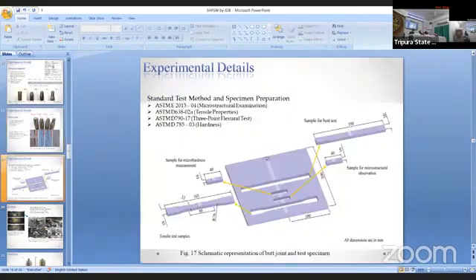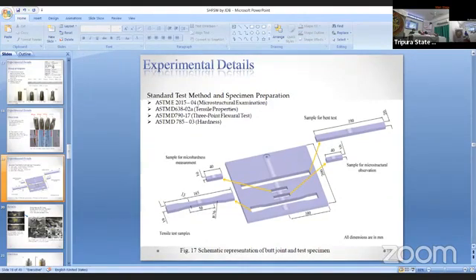For testing the quality of the weldment, we have used different standard test methods and specimen preparations. For example, for microstructural examination, we have gone for ASTM E2015. For the tensile property test, we have gone for ASTM D638-02a. So these are the different standard test methods and specimen preparations we have maintained.